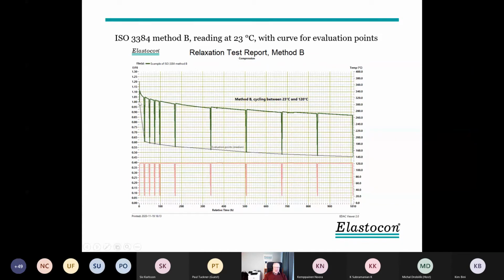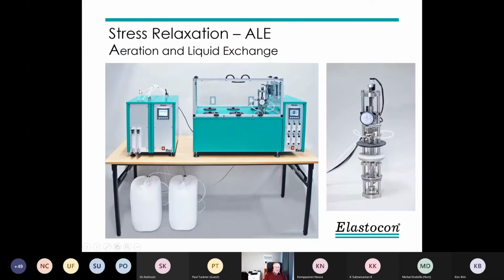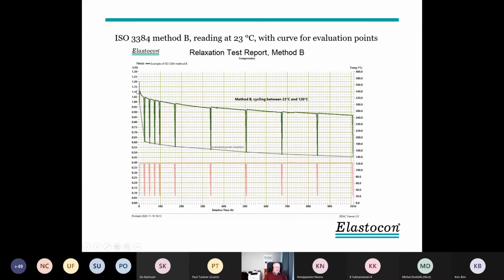When we increase temperature, in this case only to 120 Celsius, the force goes up due to the volume expansion of the rubber. Sometimes it can go up to even twice the original force if you go very high in temperature. And then we have the first down here. And now we can also plot this curve. That was from the graph before. We got these values. And we have the temperature. In this case, it's shown below. So now we can do also method B automatically and have the computer finding the values and this program the cycling in the oven.